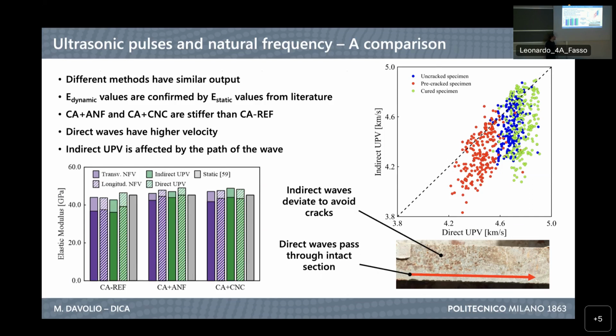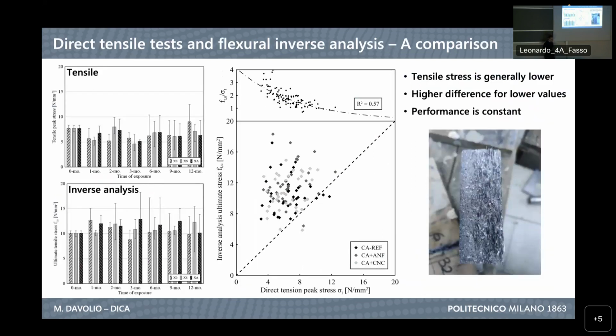We have some differences, especially between the two ultrasonic pulse methods, due to the path the waves have to follow inside the specimen. Because of course, while direct waves can pass through the undamaged section, the indirect waves are more affected by the presence of cracks or sealing on the top layer, which is the tensile phase of the section. And this is why we have some faster traveling time for the direct waves compared to the indirect ones. And for the two methods proposed to determine the constitutive law, the constitutive response of the material, there is a clear increase of the properties in the case of inverse analysis if we compare to the direct tensile test.